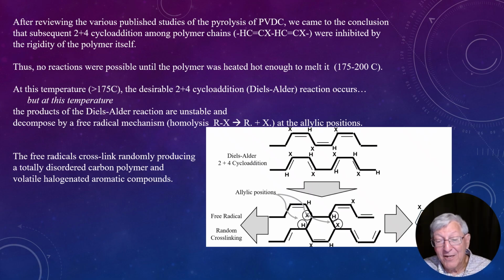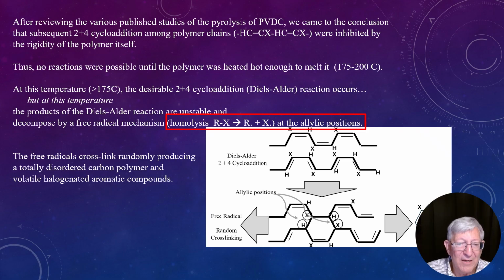And we think that the reason you have to heat it up is because the polymer itself is rigid and doesn't allow the chemical reaction to occur because it's in a rigid polymer. And so once you heat the polymer up and melt the polymer at 175 to 200 degrees Celsius, then this reaction can occur. The 2+4 cycloaddition can occur. But at this temperature, when you get up to 175 degrees, the 2+4 cycloaddition creates allylic halogen positions, which I've marked in the graphic here. And basically, they can undergo homolysis. In other words, the carbon-halogen bond just breaks.